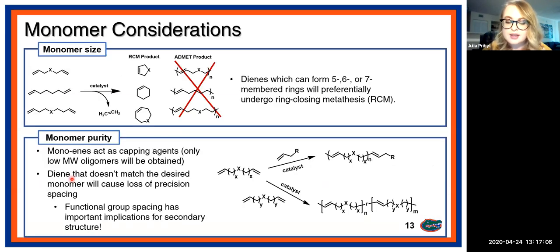A couple of other things to consider for ADMET polymerization are the monomer size and monomer purity. So you need to choose alpha-omega-diene monomers that don't form 5, 6, or 7 membered rings if they undergo ring closing metathesis. And the reason for this is that once you form these stable ring structures, they don't want to open again. So you're preferentially going to get the ring closing product rather than the desired ADMET products. You need to choose dienes that are a little bit longer than this to have successful ADMET polymerization. And also the monomer purity is of utmost importance in ADMET polymerization.